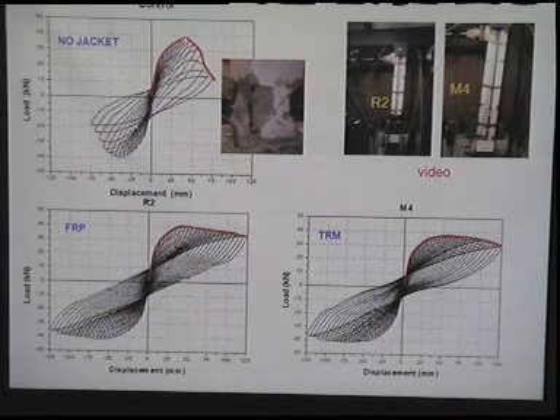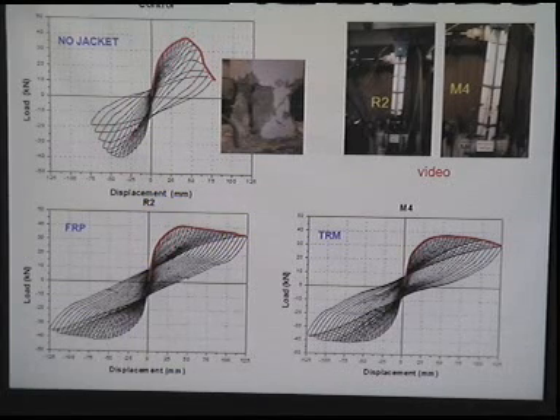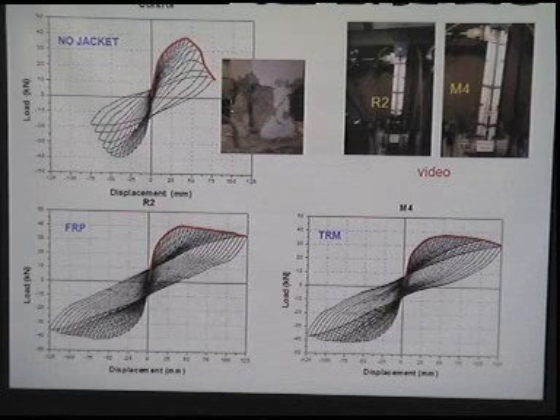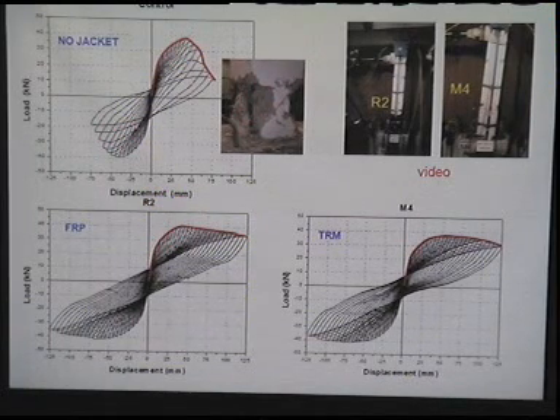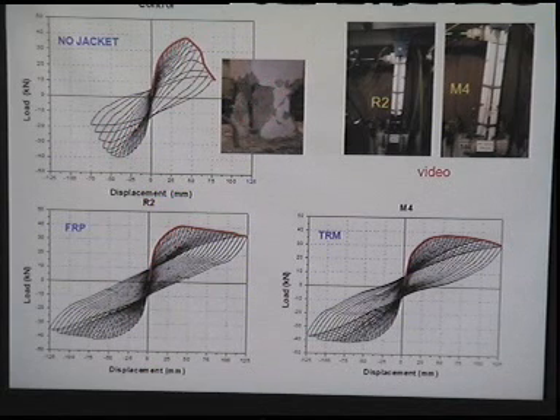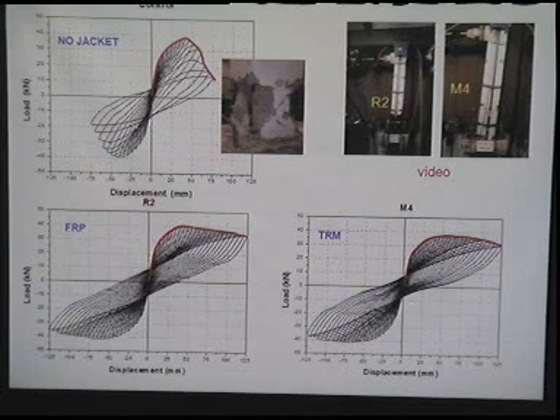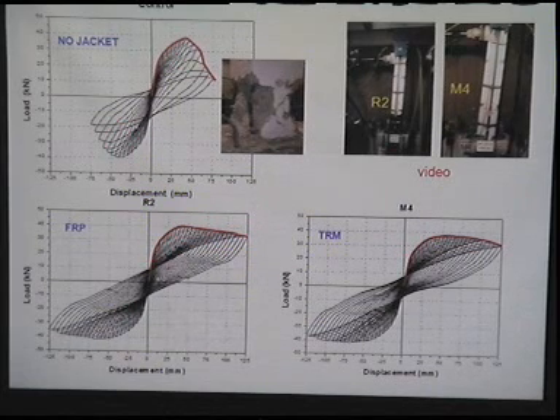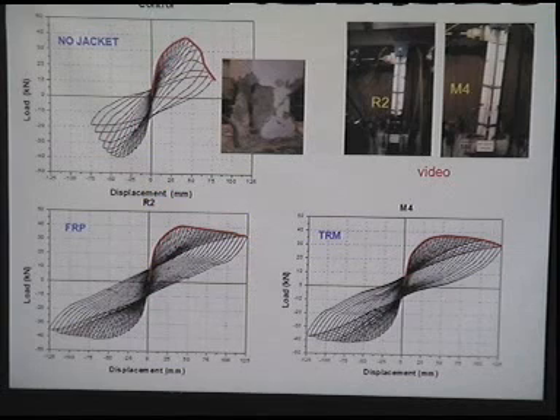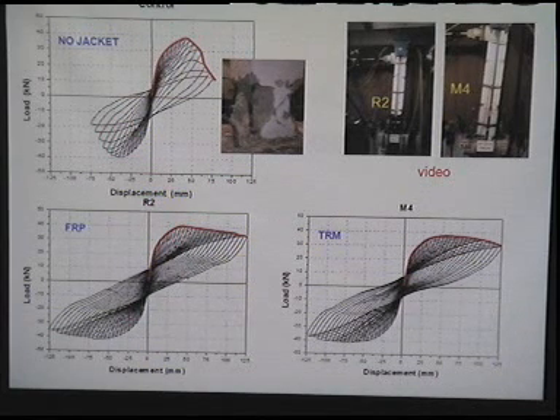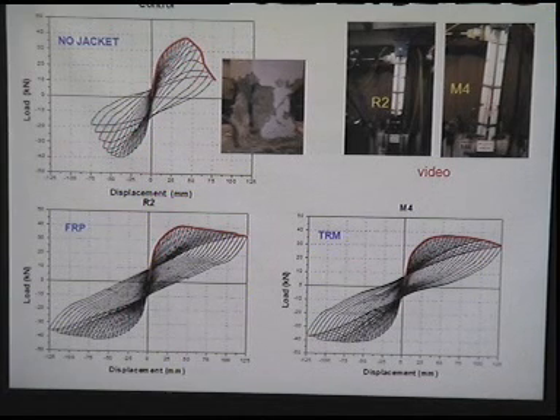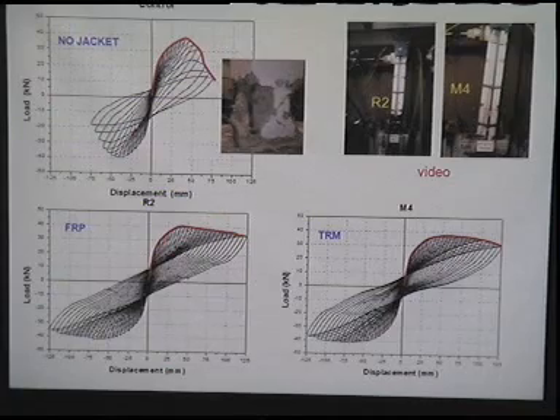We have a relatively sudden fall in the strength, reduction in the strength due to buckling of the longitudinal reinforcement at the base of the column, in the unjacketed member, in the one without the jackets, whereas in the case of the FRP or the TRM jacketed columns, we have a much better, much more ductile response with stable hysteresis loops and the dissipation of a substantial amount of energy. So we could conclude here that the two systems are practically equivalent and much better in terms of deformation capacity in comparison with the control specimen.